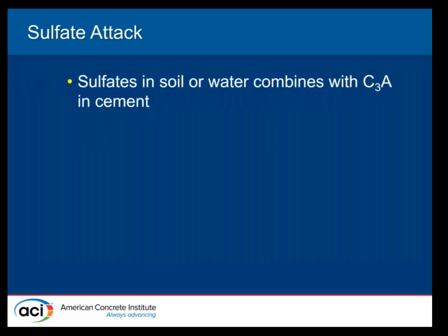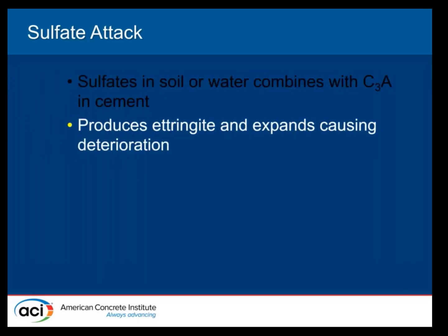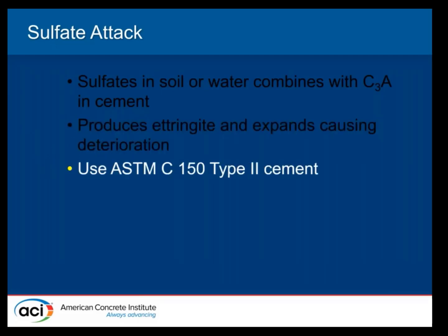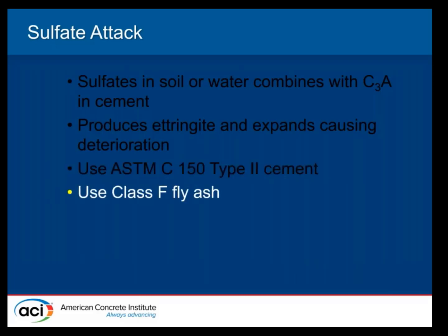All right, so sulfates in the soil or water combine with tricalcium aluminate in the cement. They produce ettringite, which causes expansion and deterioration. To prevent sulfate attack, you can use a type 2 cement, or these days it'd be a type 1L cement. You could add in a class F fly ash.